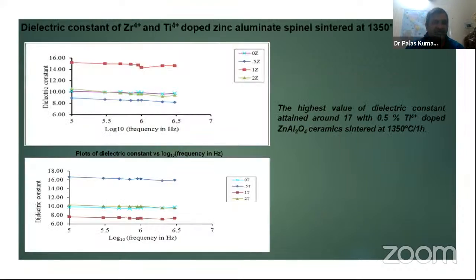First of all, the dielectric constant. Here, the dielectric constant is measured with frequency, and we selected a moderate range of frequency, 100 kilohertz to 3 megahertz, and we took the log version. This is the conventional practice, and we see that for titania we have a dielectric constant of 17, and for zirconia 15. The theoretical value of the dielectric constant of pure zinc aluminate spinel is 10.6. So the dielectric constant is increased by more than 50% after addition of the dopant.